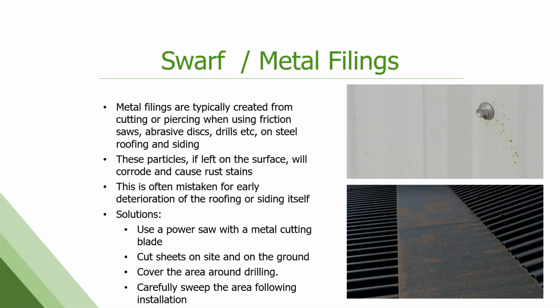Swarf and metal filings is an installation issue that we deal with on a pretty regular basis. These are little metal shavings and filings that come from drilling the fasteners in or cutting panels on a site that are then not cleaned up. These little particles get on the surface and they start to rust. Most people think it's their panels rusting, but it's actually these little swarf particles that are rusting, but they leave a permanent stain on the surface that's very, very hard to get off. And often the panels have to be replaced because of that. So we have a whole technical bulletin on that about how to cut properly, how to clean up immediately after, and if you do see some of this swarf developing, what to do about it quickly.